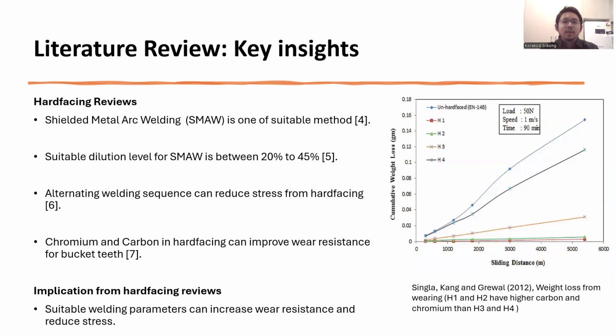Next, let's focus on hardfacing techniques. Shielded metal arc welding is one of the commonly used methods for applying the hardfacing. Studies have shown that factors like dilution levels and welding sequence significantly affect the quality of the hardfacing layer. For instance, an appropriate dilution level set between 20% and 45% can improve wear resistance, and an alternating welding sequence can reduce residual stress when compared to the linear sequence.